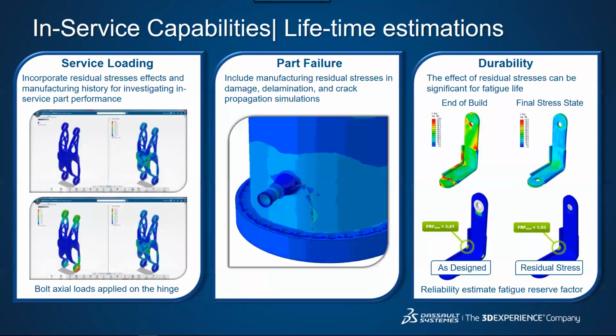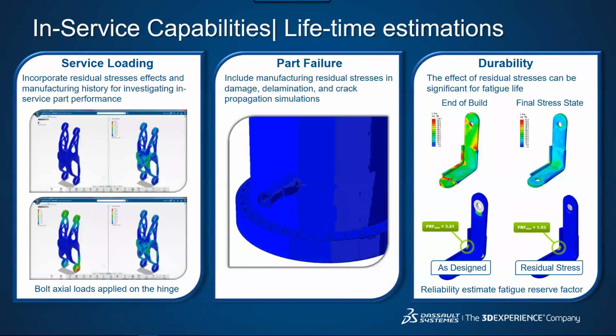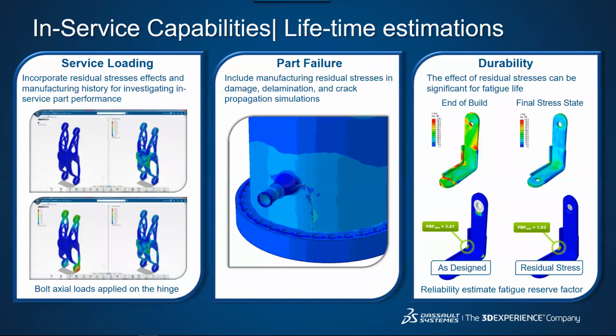Okay, so I mentioned earlier that one of the strengths of our solution is that the process simulations are built upon our comprehensive nonlinear finite element solver. As a result of that, we are also able to do in-service loading of the additively manufactured part, because we can import the residual stress effects from the manufacturing history into our service loading simulation. Part failure and part durability are largely affected by these residual stresses from the manufacturing. So the ability to incorporate them into our subsequent in-service loading type simulations is really important.